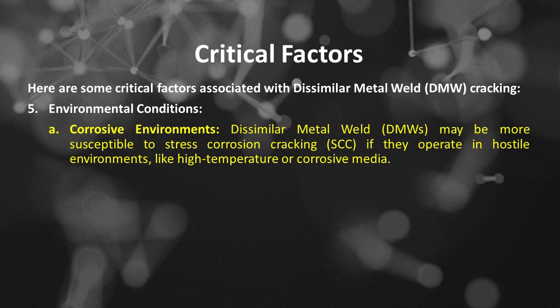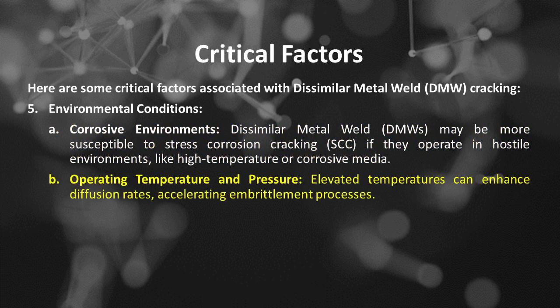Dissimilar metal welds, or DMWs, may be more susceptible to stress corrosion cracking, or SCC, if they operate in hostile environments, like high temperature or corrosive media. The second is operating temperature and pressure. Elevated temperatures can enhance diffusion rates, accelerating embrittlement processes.